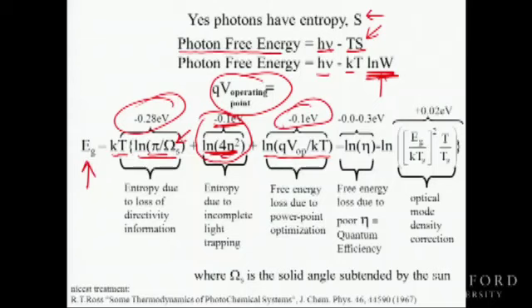So we lose another tenth of a volt, and then we can lose a huge amount if the material is not very good. There's effectively a lot of uncertainty and disorder if the material doesn't luminesce well, as you could lose anywhere from 0 to 0.3 volts that way. And some solar cells that are highly touted lose the additional 0.3 volts. And then there's some minor corrections, which I won't get into.